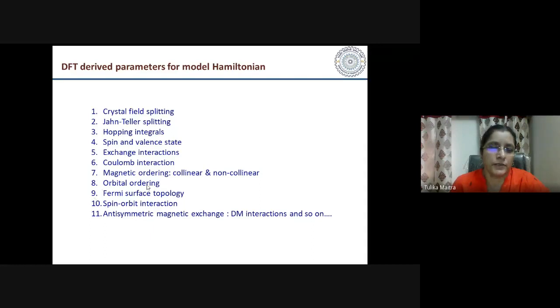You can look at the Fermi surface topology. Then you can calculate or estimate the spin orbit interaction strength. The ab initio spin orbit interaction strength can be estimated from these calculations. And further, for magnetic materials, you can also calculate antisymmetric magnetic exchange like Dzyaloshinskii-Moriya interactions and other single ion anisotropy interactions, and all that you can calculate.